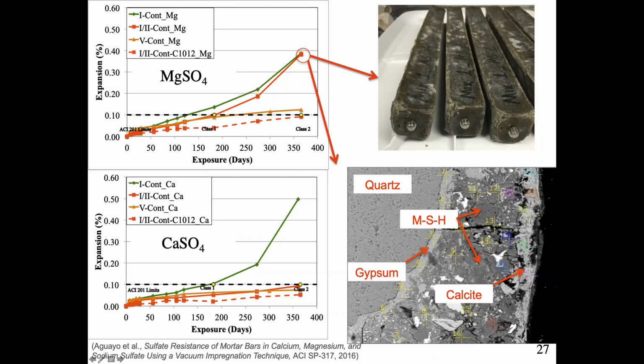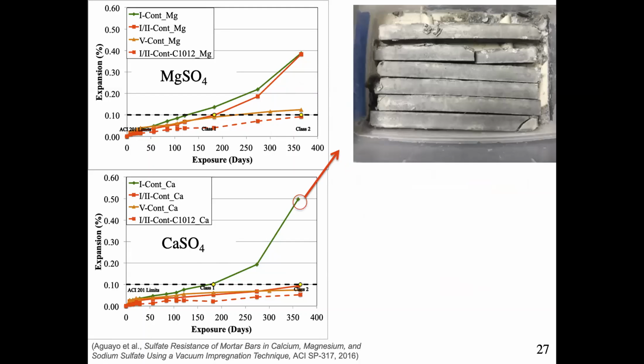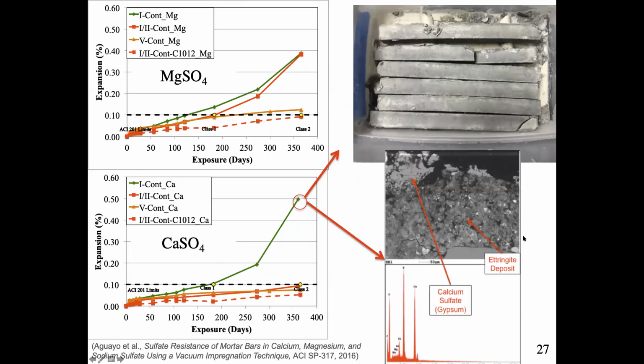We did some additional investigation to ensure that the type of chemistry or formations of the deterioration didn't change the mode of deterioration. So we did confirm that we're still showing gypsum as the main deterioration mechanism, and in terms of calcium aluminate deposits, ettringite.